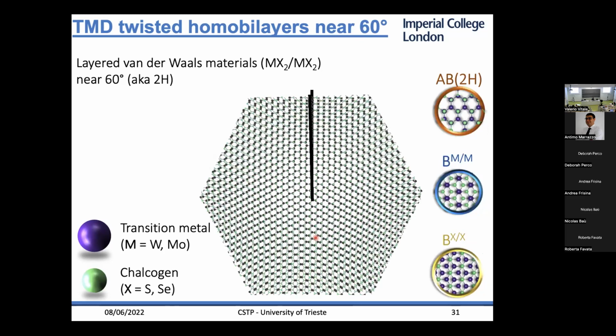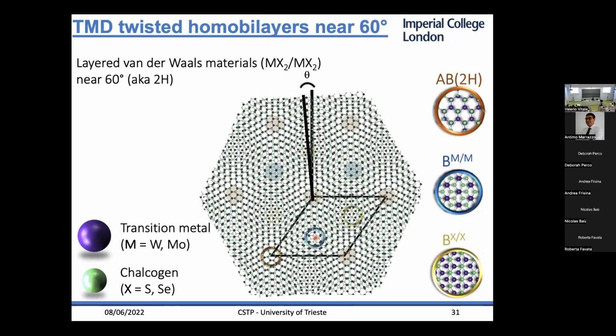But then you can start from 2H and you get a different Moiré, whereas in this Moiré, you only get these three different stackings, right? Which are different from the one I showed you in the previous slide. So this also means that these two systems will relax in a different way because you'll have different stackings in the Moiré cell, which have different energies.